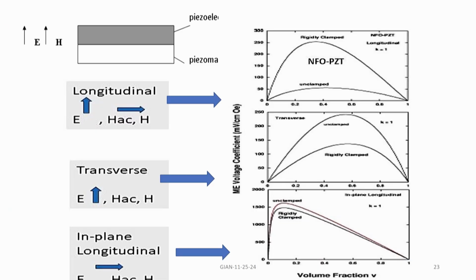When you do that, the boundary conditions at the interface will change. That will change the magnetoelectric voltage coefficient. As you see here, when it is rigidly clamped, the voltage coefficient is much higher compared to unclamped in this particular case. What is along the x-axis is, in this composite, how much PZT and how much ferrite is present. This V is the volume fraction for the piezoelectric phase. If the volume fraction is 0.2, that means it is 0.2 for PZT, 0.8 for nickel ferrite. Okay. So, it peaks around 50-50, that is what the peak value is.